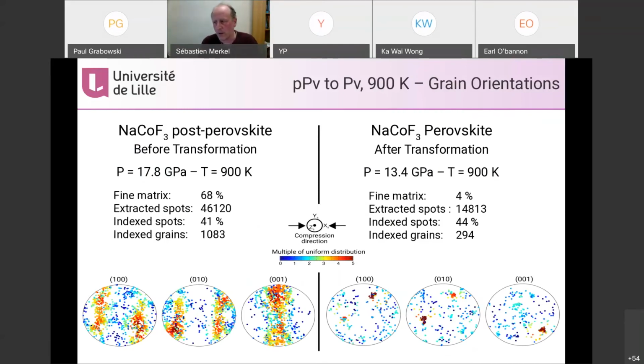You go from 1,000 grains of post-perovskite at 18 GPa. And as you go down, you go to 300 grains, 300 orientations actually in perovskite. And if you look at those 300 orientations in perovskite, they actually are very concentrated around one specific orientation for 001 and two orientations for 010 and 100. And if you look in this figure and look at the rotations to go from one to the other, you realize that to go from here to there, it's an 86 degrees rotation around the z-axis, which actually happens to be a twinning mode in perovskite.